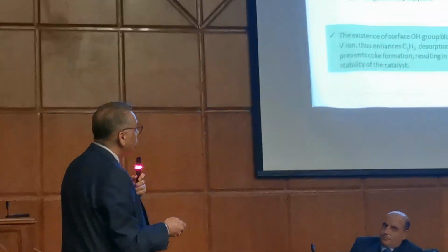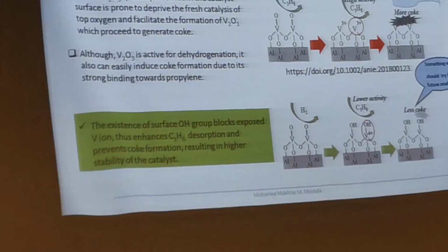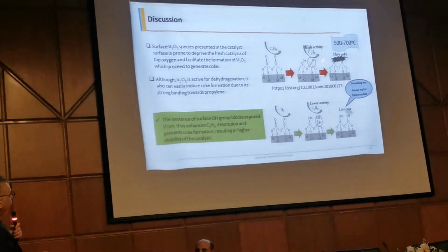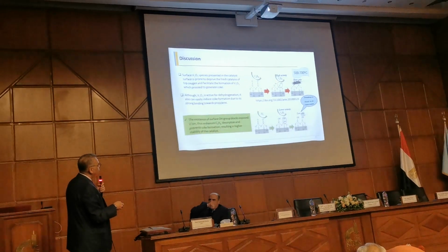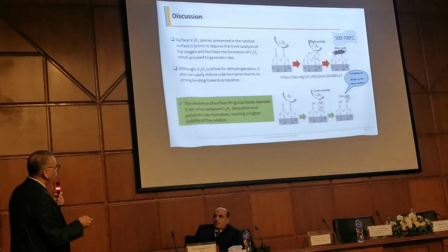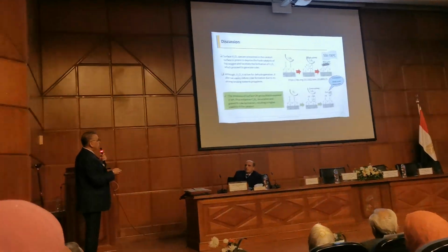And this is a very big discussion about what's possible. During our work, there were other groups working at the same time, not using the loop reactor but other reactors, but we can understand from the explanation why the deactivation takes place when they use alumina as support and vanadium, due to the formation of coke, and this coke is formed due to the presence of trivalent vanadium.